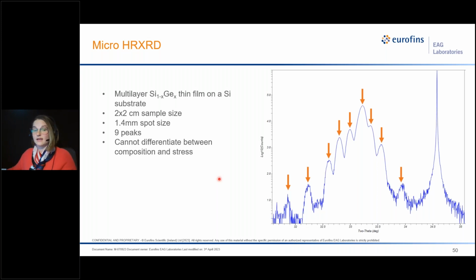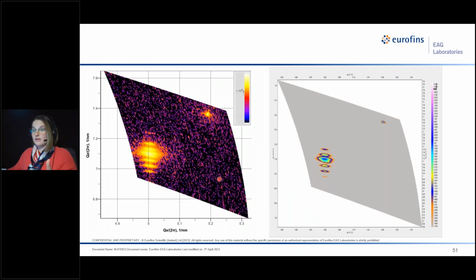We don't know if these layers have different compositions or if they have different stress. Now, these are 2 reciprocal space maps that you can see. One of them on the right is the older diffractometer we have with the standard tube. The one on the left is the rotating microfocus anode with the high brilliance source.